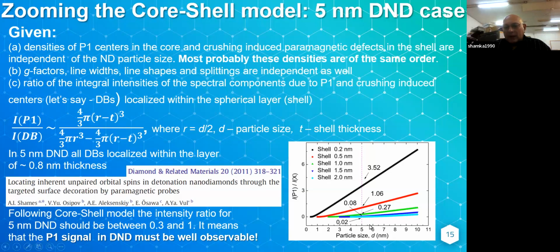Let's see what 0.8 thickness is in the core shell model. One can see that in the core shell model, the intensity ratio for a 5 nanometer nanodiamond should be between 0.3 and 1. A very, very high ratio. It should be observable.